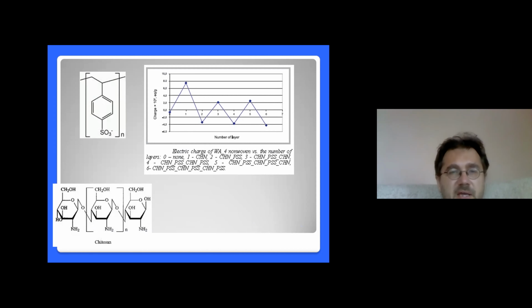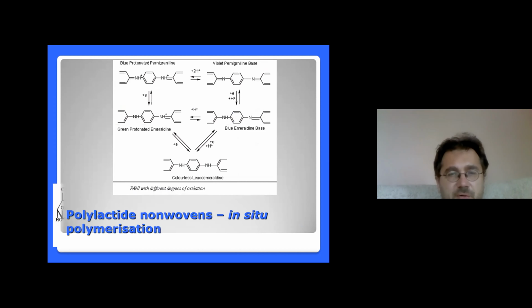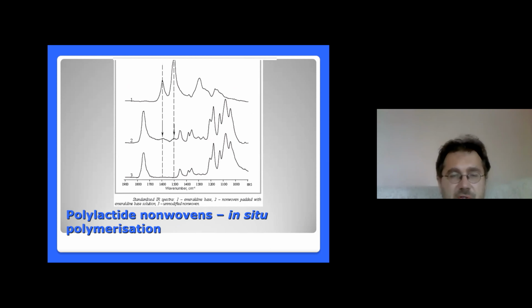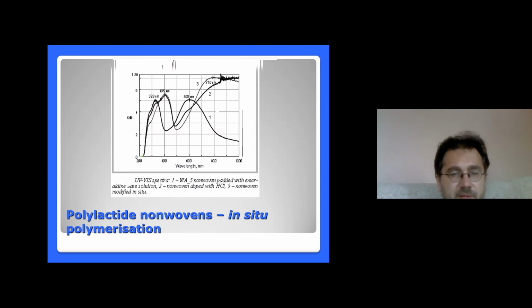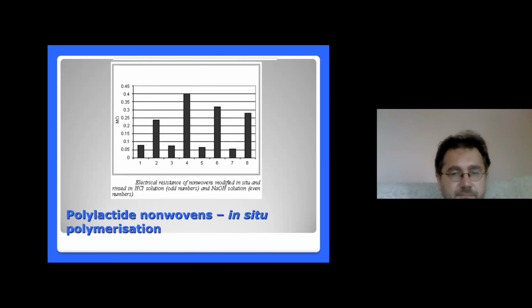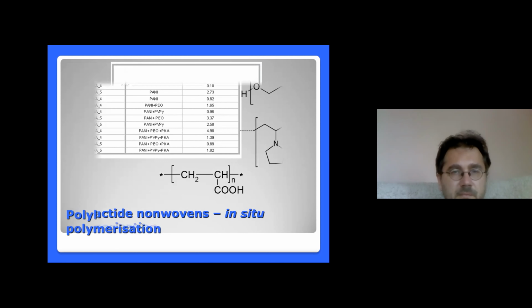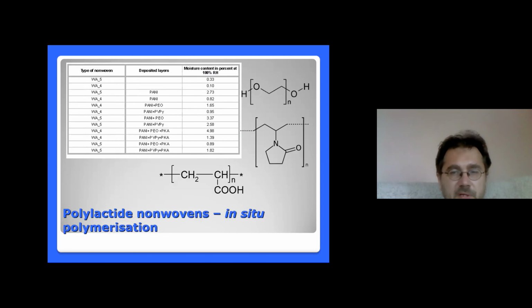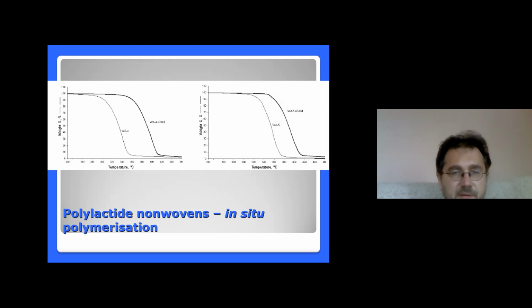Of course, the modification is changing as well electric charge and electrokinetic properties, and in one way we introduce the polyaniline on the surface. It was the procedure of in situ polymerisation, and we obtain in this way a surface with polyaniline on the external layer.